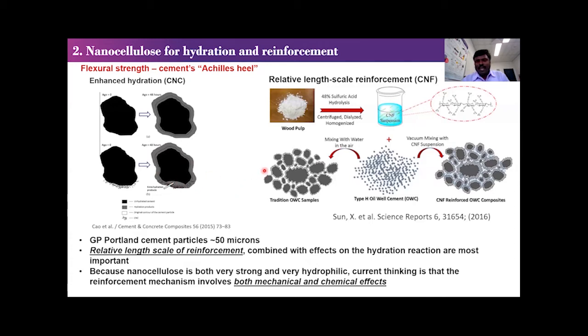That's one mechanism. The other mechanism is that if we add nanofibers, because they are nanoscale, they can act as fiber reinforcement at the nanoscale. So there are two mechanisms involved in improving the cement properties. Mainly for cement, we can increase mechanical properties like compressive strength and flexural strength. For compressive strength, we can increase it by adding a bit more cement. But flexural strength is actually a challenging one. That's where our industry partner, TMR, was interested in improving the flexural strength.